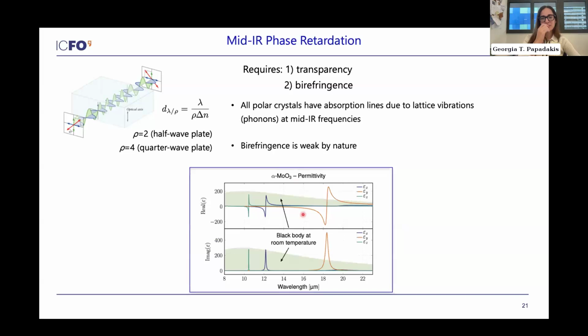However, what we did is we looked at this emerging material that is called molybdenum trioxide. And as you can see here, where we show the permittivity along the X, Y, and Z directions, it's very different. So in the X direction, it has a resonance or a phonon around 10 microns. But in the Y direction, it's a different frequency. So this material on resonance is actually extremely anisotropic, and it has a birefringence that is roughly 8, whereas most materials have a birefringence that is on the order of 0.1.